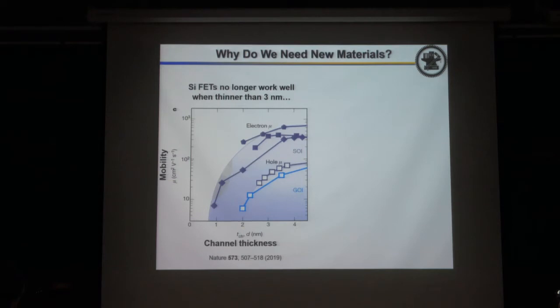Why doesn't it work? Because silicon is a 3-dimensional crystal. It has some surface states and may trap some charge at the surface. So if you reduce the thickness to, for example, down to 3 nanometers, the electron will see many charges trapped at the interface, and the Coulomb potential will block the electron from moving. So eventually, the electron cannot move in very thin silicon. That's why we have to find new opportunities.